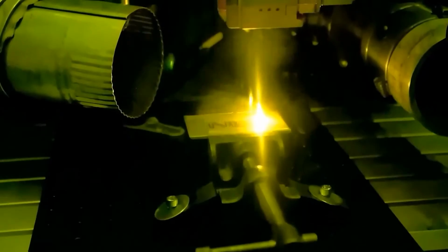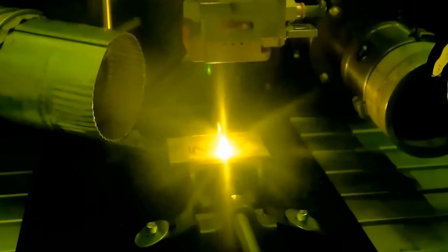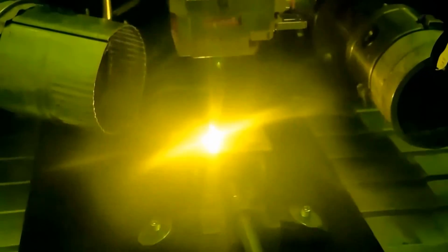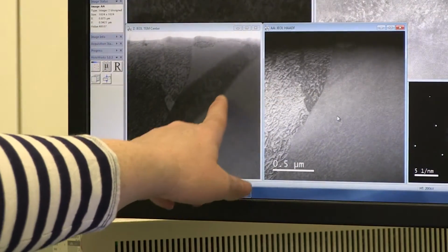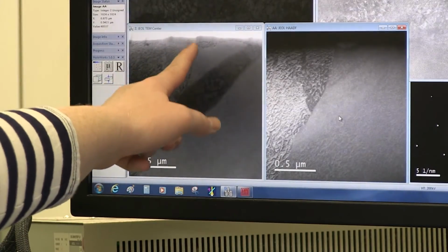In fiber laser welding, the welds are very small and the laser power is very high, and so we get very fast heating and cooling rates. What we want to understand in this project is how those cooling rates affect the final weld that you get. It turns out that in almost all materials, actually, the precise placement of the atoms can affect the macro scale properties that you and I can observe with our eyes.